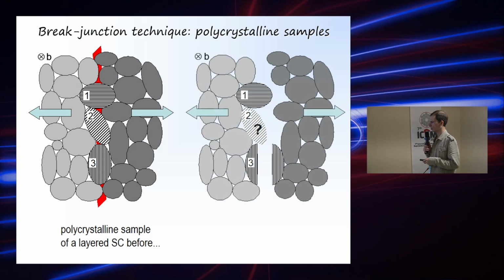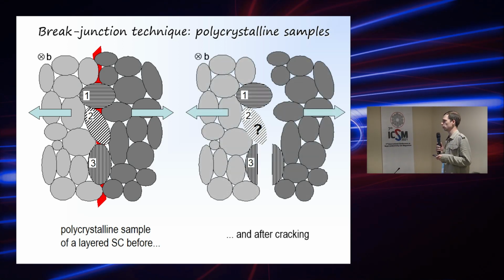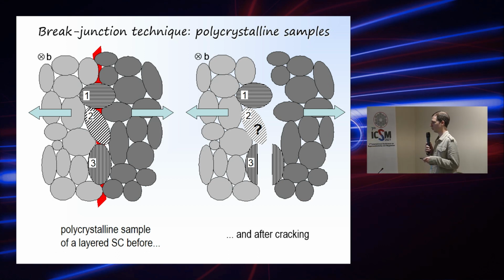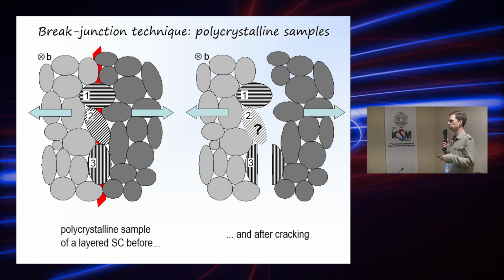This animation was done for the single crystal, but the same will work also for the polycrystalline sample, and some sketch is presented there. Here you see 3 example grains of the polycrystalline sample, and this red line is the direction of the crack that would be produced. But the orientation of layers, the key word here is layers. It will work only for the layered sample. When layers are parallel to the crack, the grain should be cracked, and in the opposite case, no. But what happened to the grain number 2?